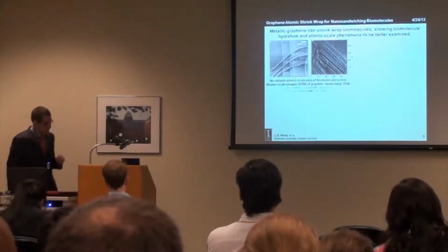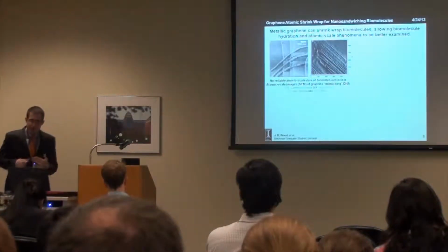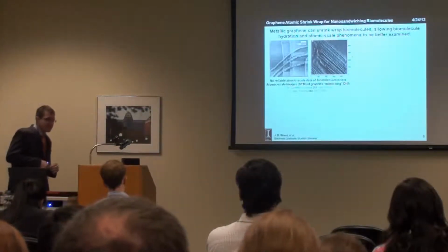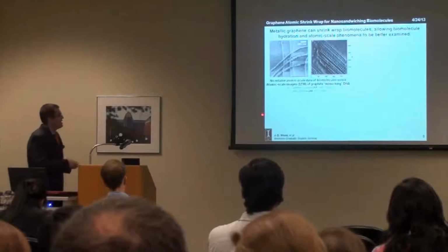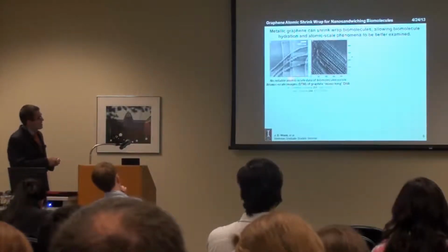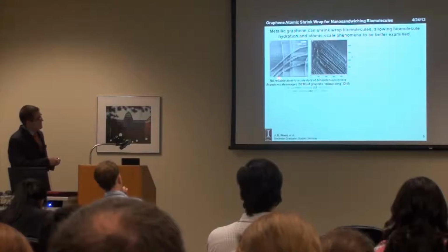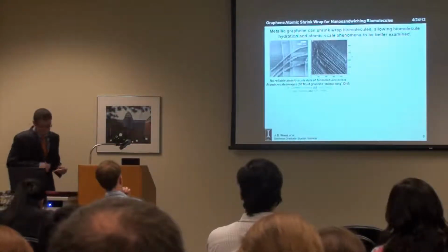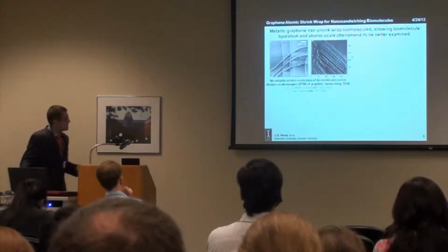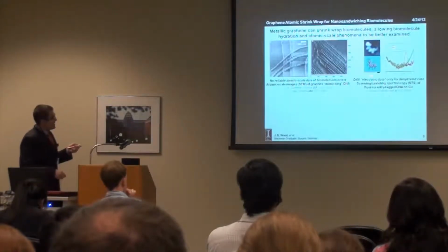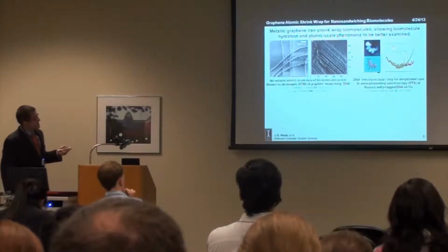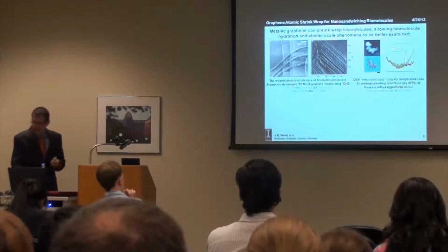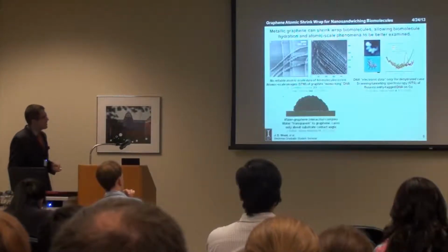Scanning probe microscopy to get atomic level information of biomolecules has been pretty hotly studied for 20 years, and essentially no one has gotten very good at it. The initial reports came in the early 90s, where they said, oh, we have DNA on graphite, when actually this is a feature of the graphite, not DNA at all. Several reports came out later refuting these results. Electronic data for these molecules is very suspicious. Sometimes you get these bands which appear in electronics, sometimes you don't, so it's pretty inhomogeneous exactly what the results are saying.